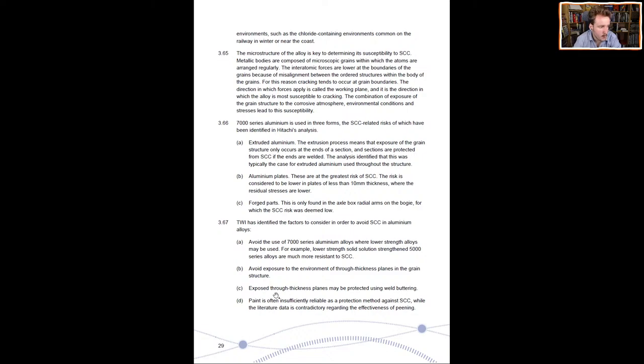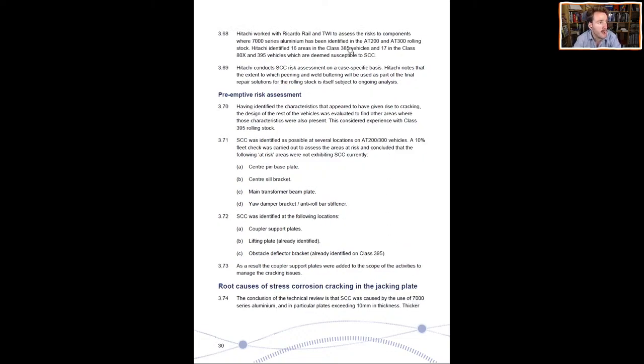They talk about using weld buttering. Paint is often insufficiently reliable as a protection method, while the literature data is contradictory regarding the effectiveness of peening. So peening may or may not be useful, and paint may or may not be that great. There's a lot of further assessment happening, and they identified quite a few areas within the 385s, the class 80X and 395s that could be susceptible to stress corrosion cracking. So there's clearly an ongoing risk here about stress corrosion cracking.